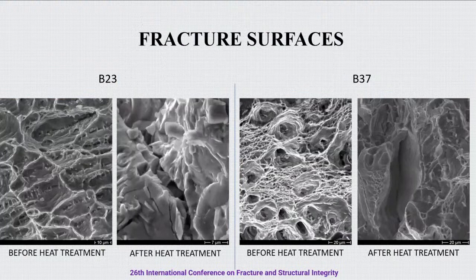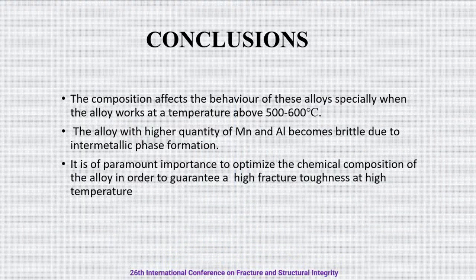Coming to the fracture surfaces for both alloys, B23 and B37. Before the heat treatment, they show a very ductile kind of fracture, while after heat treatment, B37 shows a ductile fracture, while B23 shows a very brittle fracture. I can conclude that based upon the composition of the alloys, when the alloy works above 500 to 600 degrees Celsius, the alloy with a higher quantity of manganese and aluminium becomes brittle due to the formation of intermetallic phases. It is very important to optimize the chemical composition of the alloy in order to guarantee a high fracture toughness at high temperature.